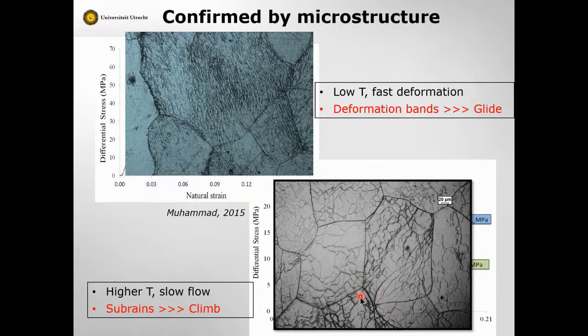So what does this tell us? It tells us that during deformation at pretty low strain rates, around things like cavities or in natural deformation of salt, you would expect climb to be the main mechanism of crystal plastic flow, dislocation flow. And right up against cavity walls, where the stresses are very high and deformation is fast, you might expect glide. This is what you expect to be dominant.